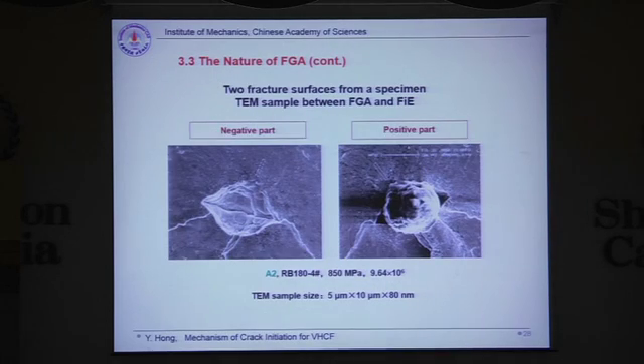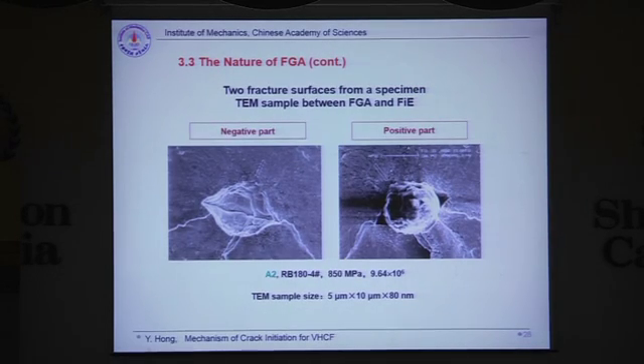And then we observe another specimen, the green specimen, and we use both fracture surfaces. This is the negative part and positive part of the fracture surfaces, and we cut the FIB sample from almost the same location. We just try to see how the morphology is on both sides of the specimen.